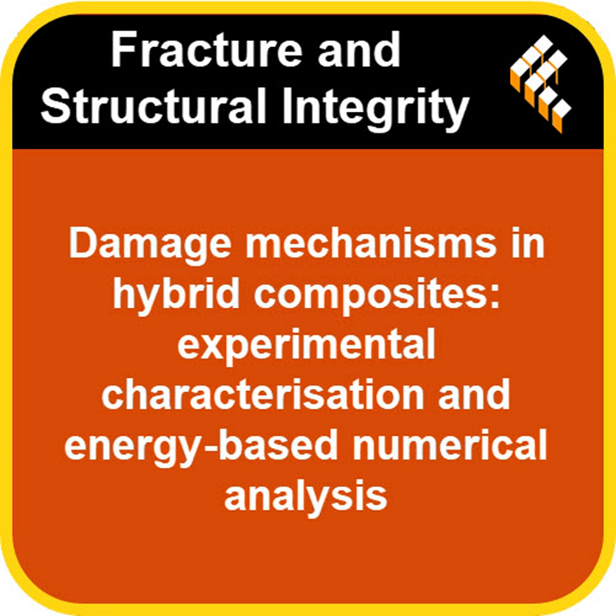And what about those samples that were purely carbon or purely glass? Where did the damage tend to start in those, according to the models? In the pure carbon material, 8C, damage first popped up in the outermost layers on both the stretched and squished sides, layers #1 and #8, at roughly the same time, and then it spread rapidly through the other layers. Okay, fast progression in pure carbon. Yes. In the pure glass material, 8G, the damage also started in the outer layers, first on the compression side, #8, then the tension side, #1. But the progression was much more gradual compared to the carbon. Interesting difference in